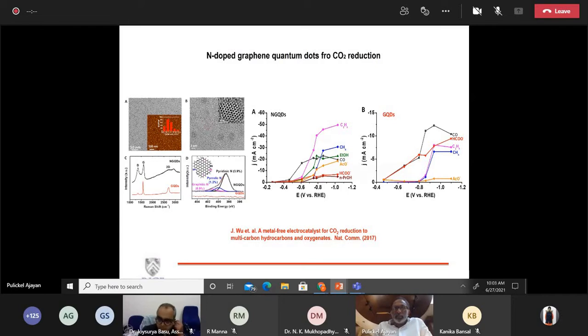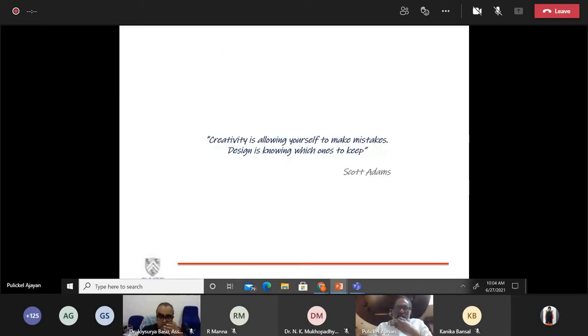And of course, CO2 reduction is an important technology that is coming out now. And the only real good catalyst is based on copper, but metal catalysts are always problematic because of stability and so on. And the carbon-based catalyst seems to hold some promise in this area as well. So let me kind of end here. Essentially, what I showed is a lot of examples from various stages of our work in the last 2 decades or so, showing that you can not only make some of these building blocks, but also you can create some engineered structures using these building blocks.